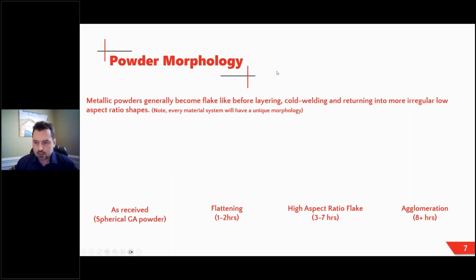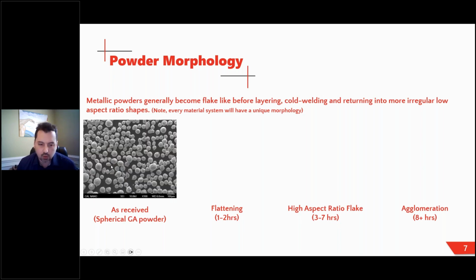So what does the material actually look like? There are many stories. This one will just be covering an example of starting from a spherical powder. So we don't have to start from spherical powders. We typically start with materials in this process in conventional powder, thermal spray type grade powders from 20, 30 microns up to 200 micron type range, similar to the additive manufacturing type starting materials. But again, sometimes we're running pure ceramics that are just crushed in an irregular shape already.